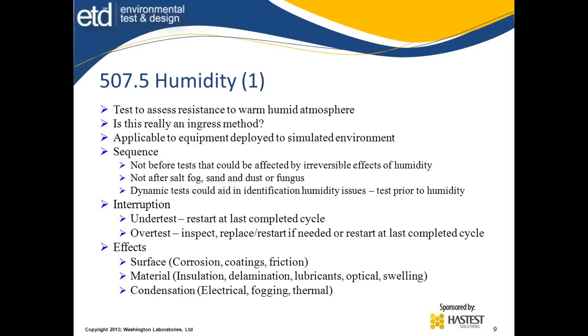And swelling of components. For any of those that are familiar with an EMC test facility shield enclosure, high humidity eventually creeps into the pressed wood holding metal plates together, and that delamination or swelling of that material causes those panels to open up, and you lose the whole shielding effectiveness of your room. It's just an example, but many things have the same kind of problem. The condensation from humidity gets to the electrical world, and the fogging also adds to the thermal effects where it tends to retain the heat.